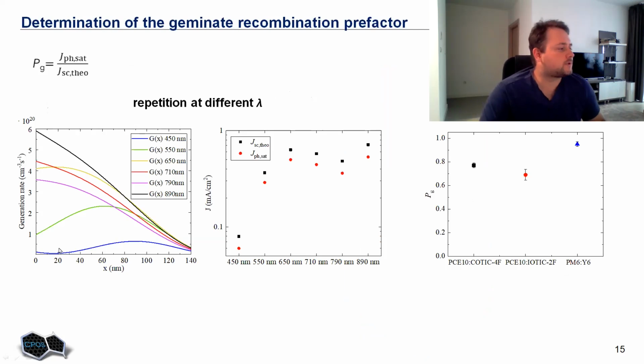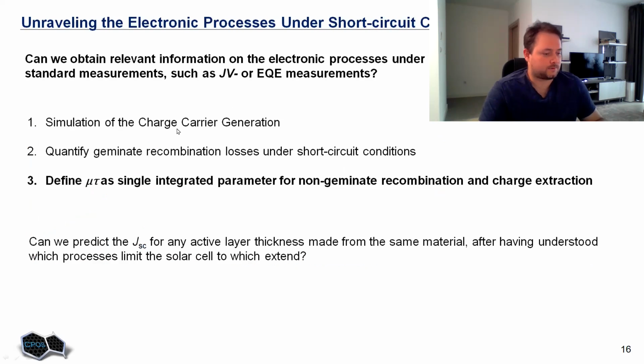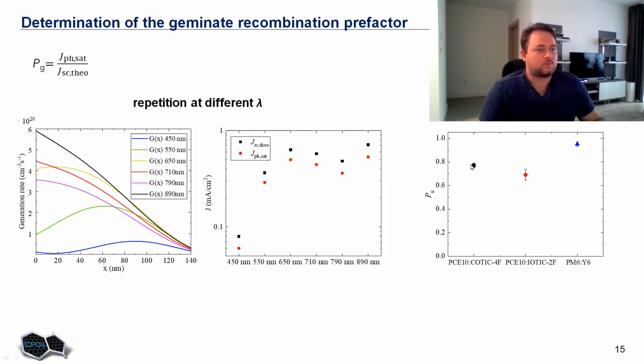So when we did these measurements, for instance, here we see generation rates calculated with the transfer matrix approach for different wavelengths. Then we calculate the theoretical current for each monochromatic illumination. And here are the experimentally measured saturated photocurrents. The ratio between the saturated photocurrent and the theoretical maximum current gives us this geminate prefactor P_G. We did it for different wavelengths and got some standard deviation, because it should be wavelength independent, for different mixtures of donor and acceptors.